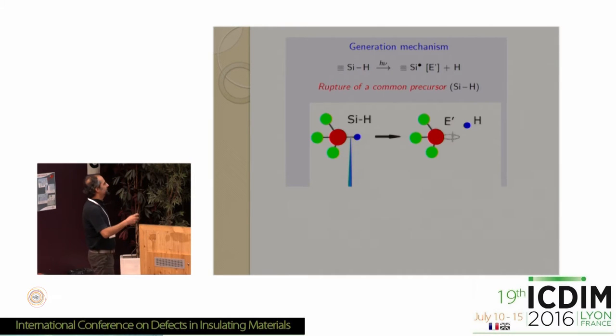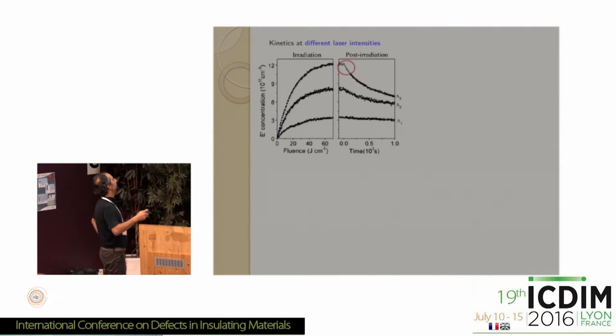Now, we studied this, and the answer we proposed is that both of them are generated by a single process. So the main event taking place in the sample upon UV irradiation is this one. You have pre-existing SiH bonds in the sample as impurities, and they get photochemically broken by laser light, generating at the same time silicon dangling bonds and hydrogen. And then what we observe in the post-irradiation stage is due essentially to the geminate recombination of the two. There are ways to see this.